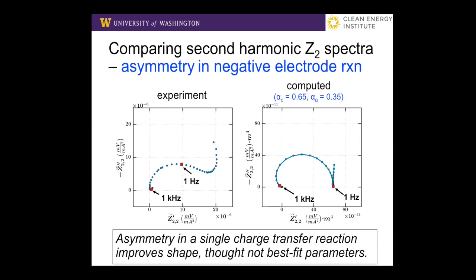But we can see that as we break the symmetry by making the negative electrode's cathodic and anodic charge transfer be asymmetric, 0.65 and 0.35 instead of 0.5, 0.5, like the standard model, we start introducing some of the feature shapes that we need. So there's more information in here than we've ever been able to really glean in the past about this. So asymmetry in a single charge transfer reaction improves the shape, though it's far from a best fit parameter.